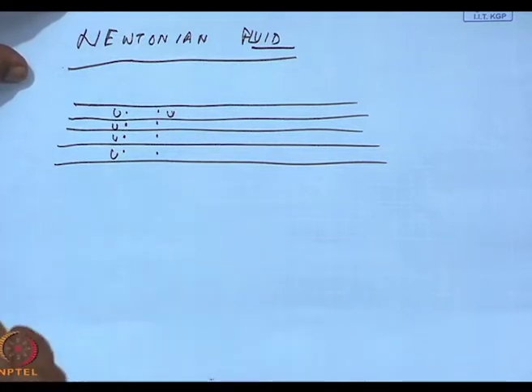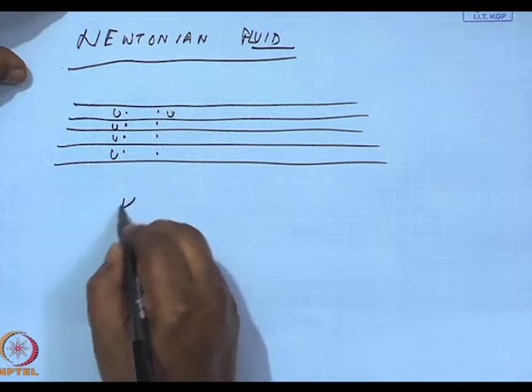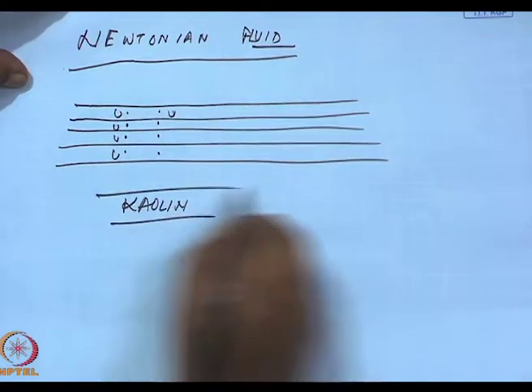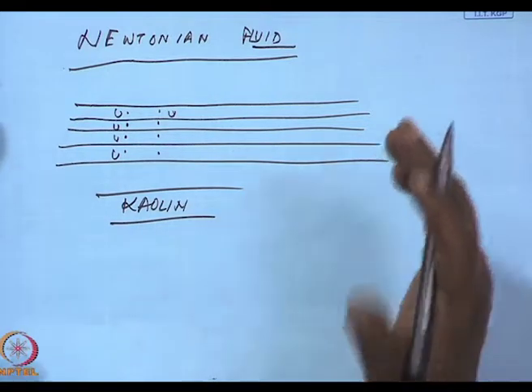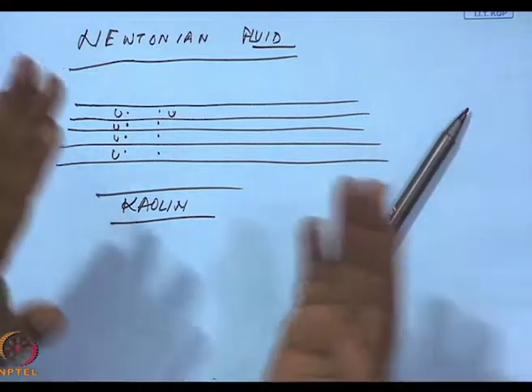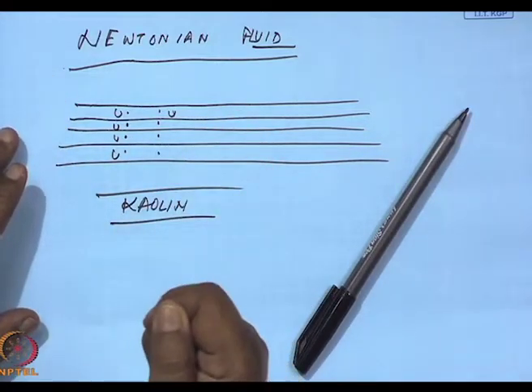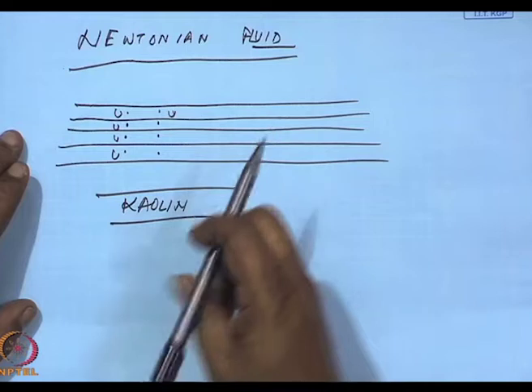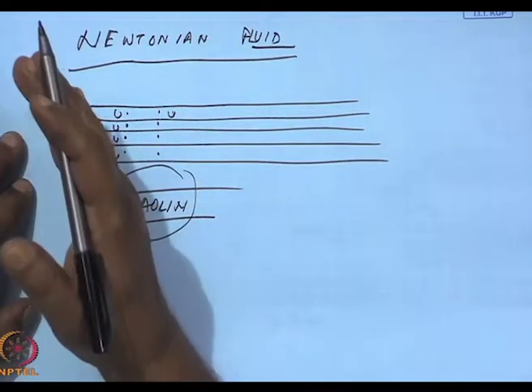So, there the best additive for alumina is kaolin. This is an excellent binder. I talked of kaolin earlier at the start of the class. They are thin platelets, hardly 10 angstrom thick, 100 angstrom across, and they form excellent binders for alumina tubes. However, the problem is due to the presence of silica, it may form low melting phases. So, if I am using kaolin as a binder for alumina tube, I can jolly well use it below 1000 degrees centigrade. Nothing will happen.